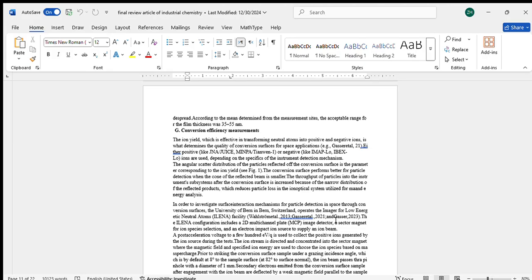The conversion efficiency of the surfaces is crucial for detecting particles in space or in the orbit industry, especially for ion detection. The performance is determined by how well the surface can convert the neutral atoms into ions. The setup involves using an ion beam directed at the surface, where it interacts with the surface, causing the emission of secondary electrons and ions. These secondary electrons or ions are also produced in the SEM. These are then measured by a detector.